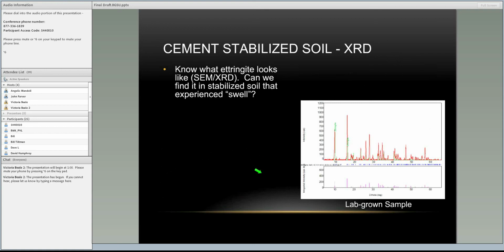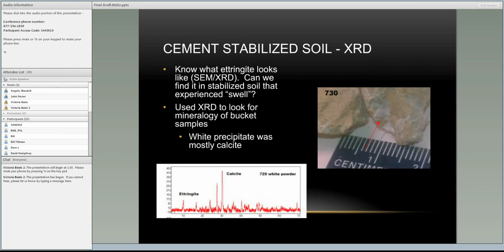So in the XRD scan below, we're looking at a sample of 729 white powder. Looking at the white powder, we did find some ettringite, but we also found calcite. And when looking at a lot of samples across the board through all the stationings, what you find is that the white precipitate is mostly calcite.